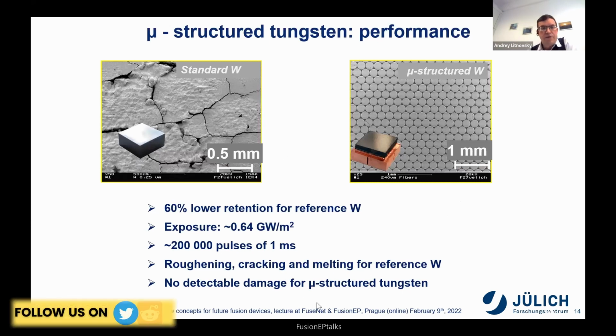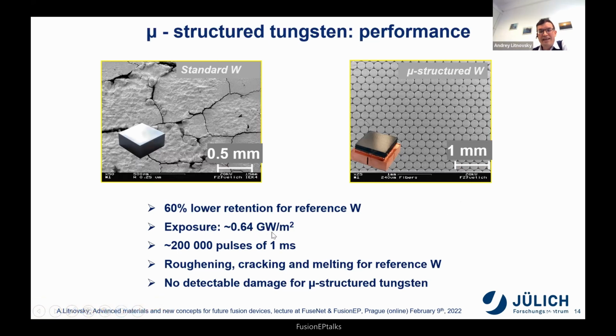To study this, laser pulses with a power density of 0.64 gigawatt per square meter were used, simulating transient effects. In total, it was 200,000 pulses of 1 millisecond applied to the ITER grade tungsten, or the tungsten made with ITER specifications, and to the microstructured tungsten. To be honest, the ITER grade tungsten showed damage after several hundreds of these pulses already, whereas the microstructured tungsten survived all these 200,000 pulses. This is an incredible number.